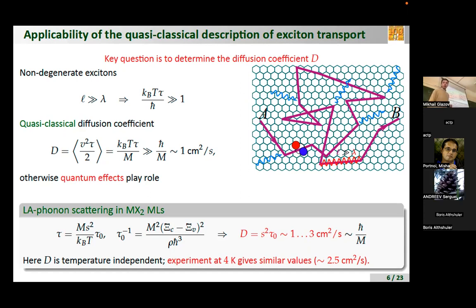And Misha, where is the exciton radiative lifetime in this slide? Tau is not the radiative lifetime. It's assumed to be very long. As I mentioned, answering the question of Alexei, especially at low temperatures, most of the excitons are dark. They are either in spin forbidden states, which are basically lower in energy, or they are in the intervalley states, and they also have quite long lifetimes. Typically, in these conditions, lifetimes could be on the order of several hundreds of picoseconds. This is the time during which the decay of photoluminescence occurs.